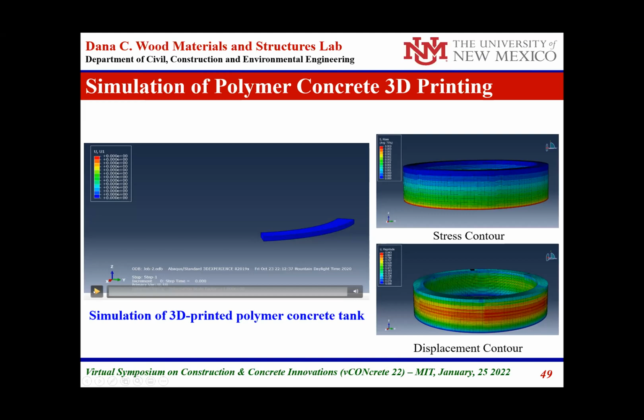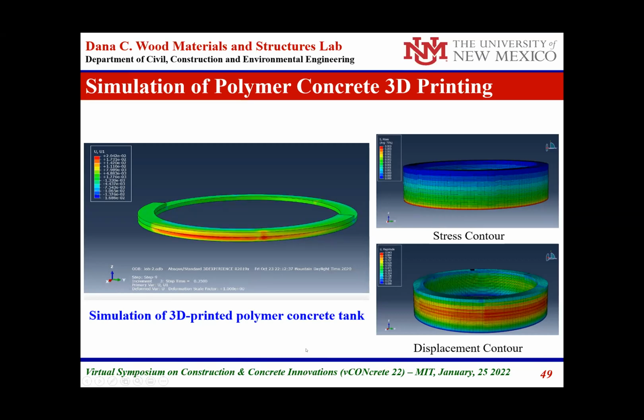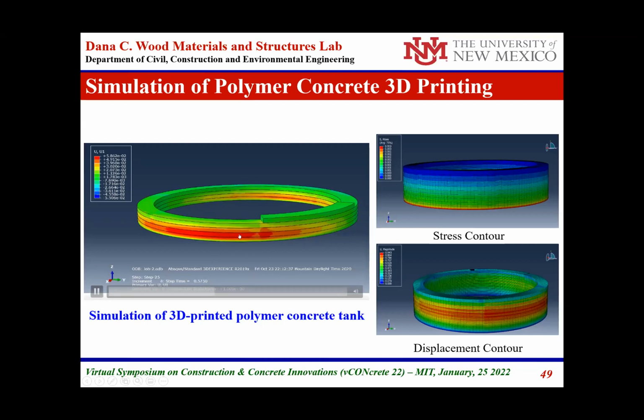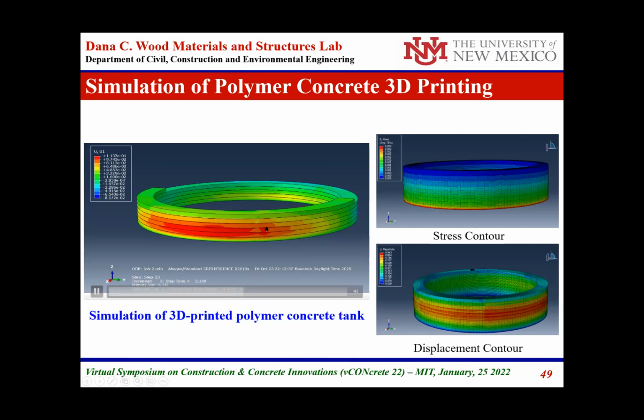Now that we have this, we can build a finite element model, because our interest is to build and 3D print a polymer concrete tank for chemical applications. With time, you can see that because we have these contours, we have the specifics of the material properties, we can simulate the process of 3D printing the polymer concrete, and we can identify the stresses, and we know the strengths, so we can identify if there could be a failure. There are other features we are adding to this model.